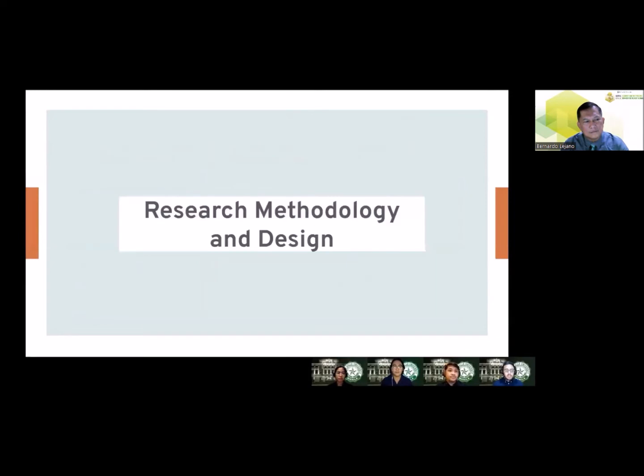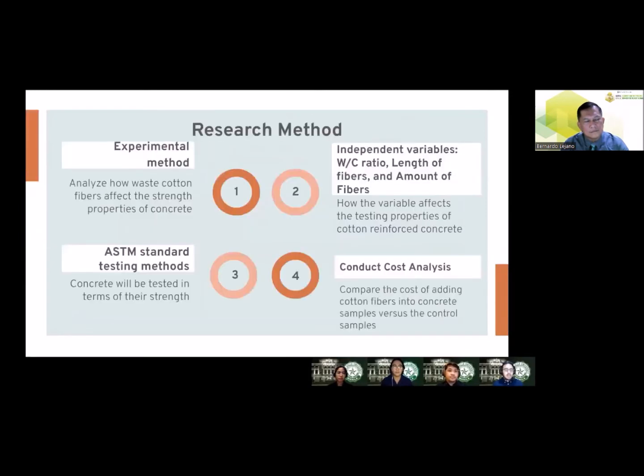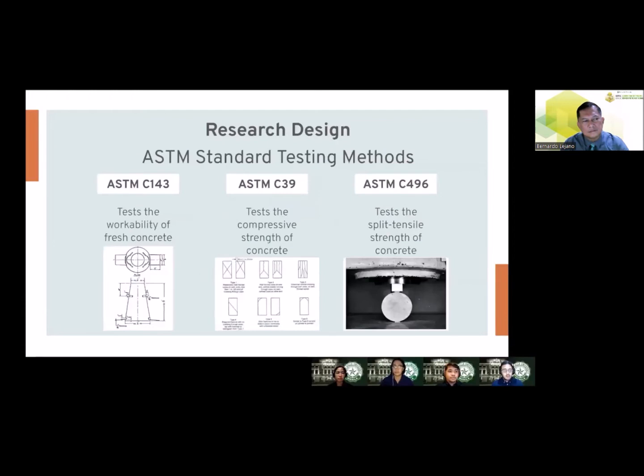For our research methodology and design, the research method involves analyzing how waste cotton fibers affect the strength properties of concrete through the use of the ASTM standard testing methods. The independent variables include the water to cement ratio, length of fibers, and amount of fibers, and these variables will be checked if it affects the testing properties of cotton reinforced concrete. Finally, a cost analysis will be conducted to determine the cost effectiveness of different concrete samples versus the control samples. There are two stages to the experimental method, the first being the workability test to determine the samples to be used for the second stage, which includes the compressive and split tensile strength test.